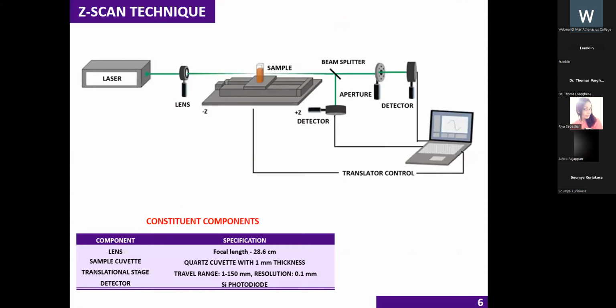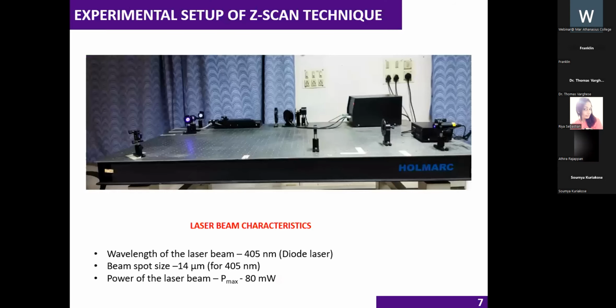Moving to the instrumentation. In the present work, the Z-scan technique is used for the nonlinear characterization of the material. For that, a blue diode laser was used. The laser beam is allowed to fall on the sample, and the sample is scanned from -Z through the focus to the +Z distance. The beam coming out of the sample is split into two using a beam splitter. In the present study, only the closed aperture Z-scan characterization is carried out, so before falling on the detector, the rays from the sample are allowed to pass through an aperture. The different components and their specifications are listed in the table.